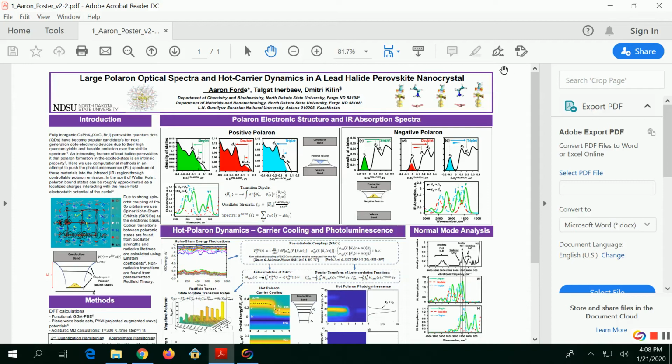So this is the perovskite system I'm working with. If you put in a charge, which are the black isocontours, so adding an electron to the box, the lattice will have a response, and that's what the little arrows represent. So it's reorganization of the lattice. What's expected to happen is similar to if you have a defect state or a dopant in the crystal, you can consider it as an effective Hamiltonian. So it's a charge interacting with a mean electrostatic field around it. It's similar to the hydrogen problem. So you'd expect the polaron to create a bound state and then have a little energy well, similar to a hydrogen well.